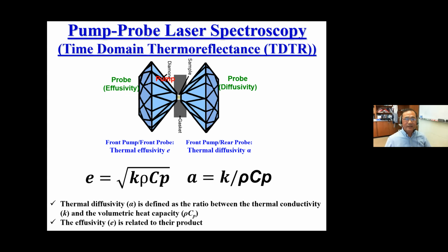Sorry. Yeah. So the traditional way is to use a femtosecond laser, but in my lab, I have a picosecond laser that I use for impulsive stimulated light scattering to measure mostly sound velocities. That picosecond laser is also used for the pump probe measurements. We call it the picosecond TDTR system. And we use a continuous wave laser of 532 nanometers as the probe beam. Okay, thank you.